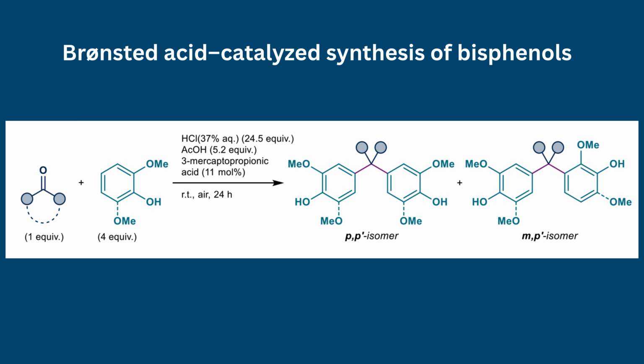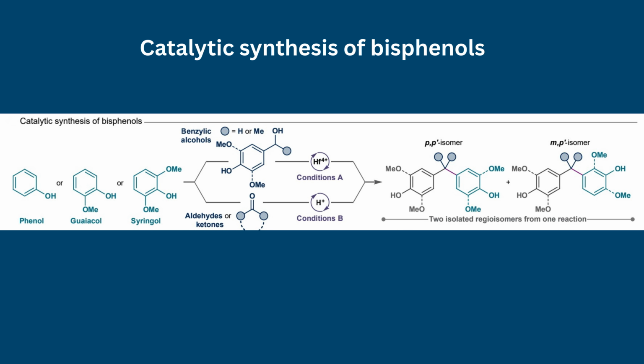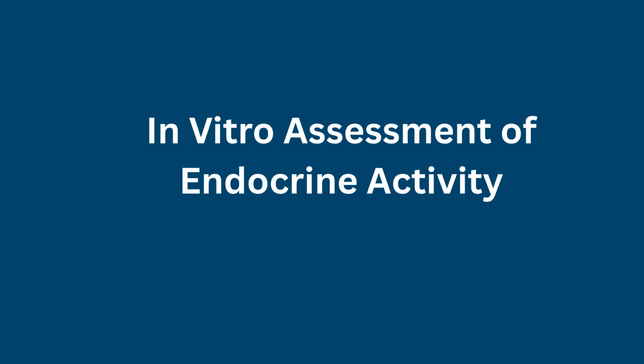Brønsted acid catalysis. Conventional acid-mediated condensation was used for more substituted derivatives. Reaction optimization included the use of renewable solvents such as 2-methyltetrahydrofuran and tuning of catalyst loadings to improve efficiency and reduce waste. Several products were obtained as regioisomeric mixtures, which were separated where necessary for biological evaluation. Catalyst recyclability was demonstrated, reinforcing the sustainability of the synthetic methodology.